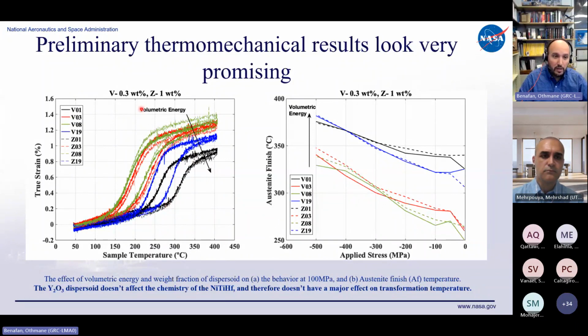But number two, 0.3 yttria and 1 yttria on this alloy, you can see them right on top of each other. The blue ones also have two curves in here. At higher energy density, you can see them start to separate a little bit. That's the effect of the laser and evaporation of some nickel and so on. On the right-hand side, you can see the austenite finish temperature as a function of applied stress, in terms of the mechanical properties. And you can see how these groupings are staying together here.